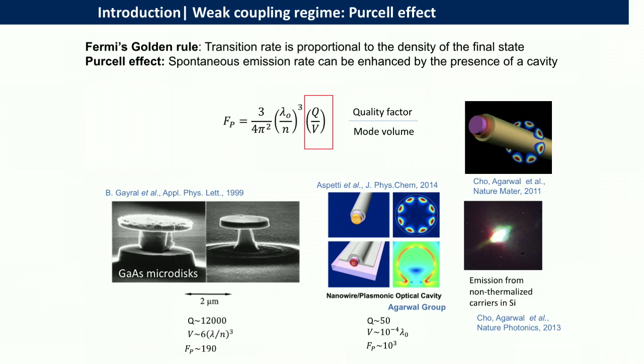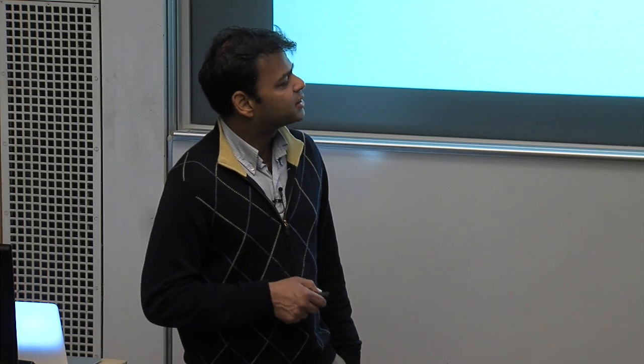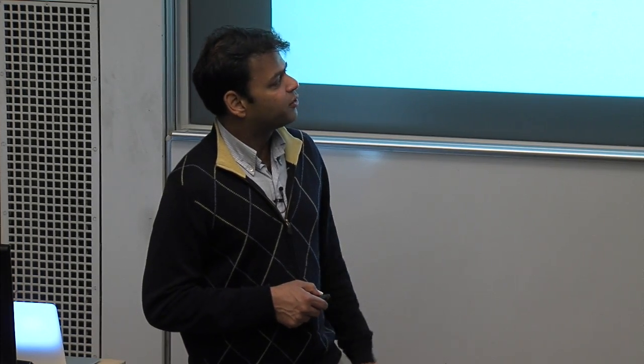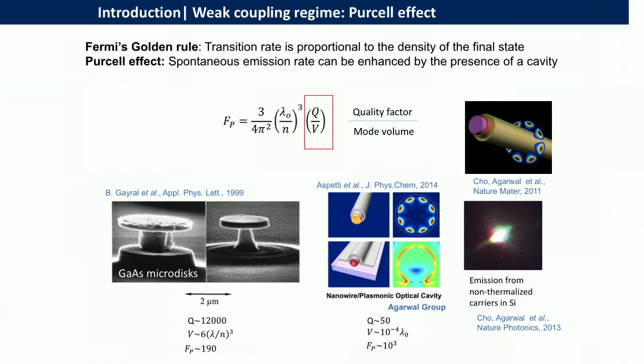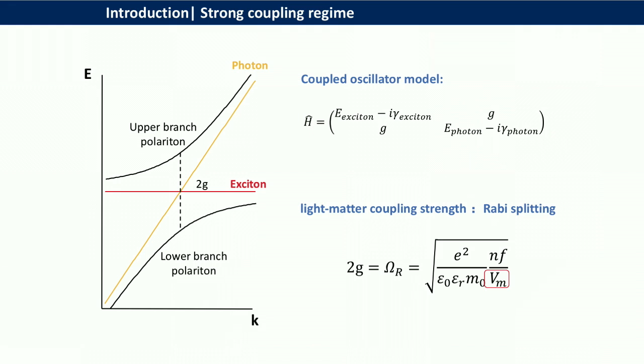But just like here, if we can make the cavity lifetime comparable to the phonon relaxation timescale, then there's a possibility of extracting those carriers, forcing them to recombine before they move too far away from the gamma point. So we utilized this idea, and we were able to make silicon emit light with an internal quantum efficiency of 1%. That's pretty large, given the fact that silicon's quantum efficiency is 1 in 100 or 1 in 1,000 at least. This is very, very small. So these are examples of the weak coupling regime and some unique applications of that.